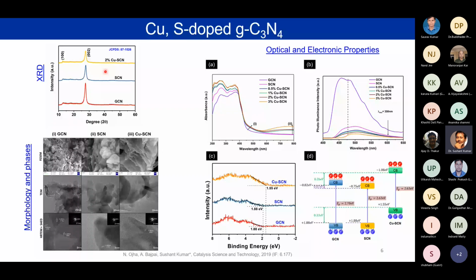So we can assume from what we see here that the graphitic carbon nitride, which initially had a 2D structure, has a reduced interplanar spacing, and also the copper and sulfur have been in the plane of the graphitic carbon nitride. This structure is in line with the HRTEM images that we have seen. You can see that we have got these planar kinds of structures for the copper SCN and SCN.